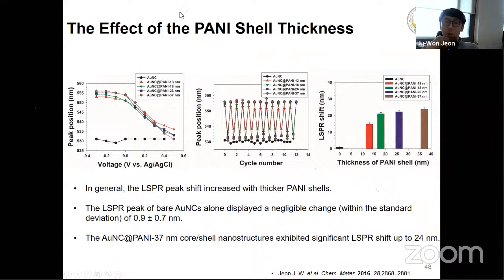So we also studied the effect of the polyaniline shell thickness on the plasmonic properties. So maybe in this graph, the LSPR shift is increased depending on the thickness of the polyaniline shell. But after some threshold polyaniline shell thickness, there is not a significant increase in the LSPR modulation, which means the LSPR sensitivity of the gold nanocube only detects the environmental change around the 25 nanometer region.